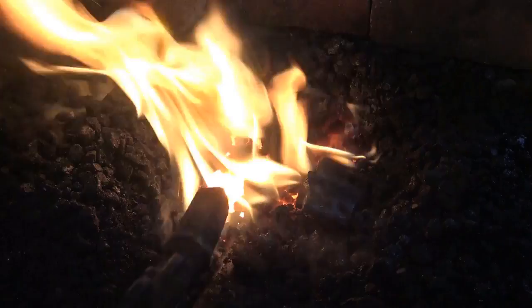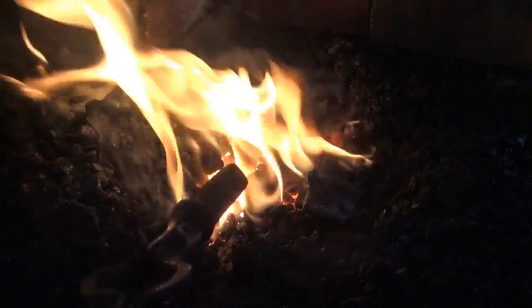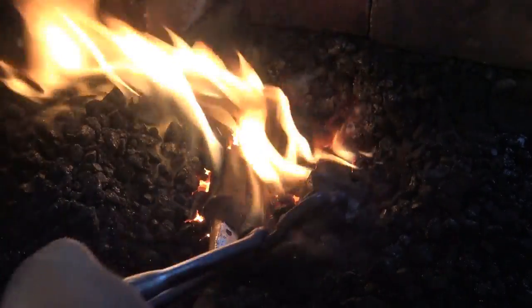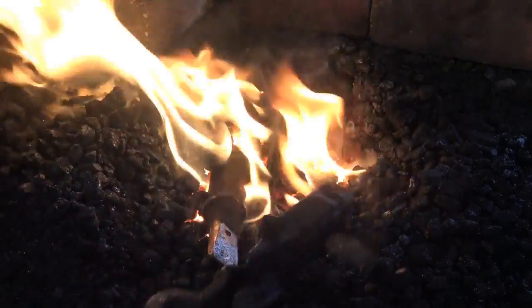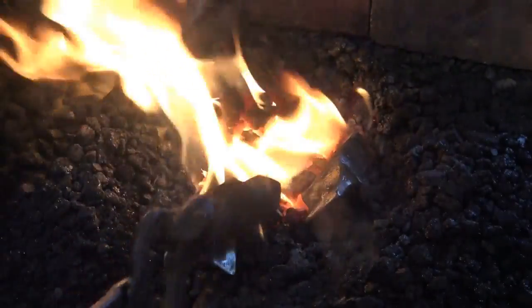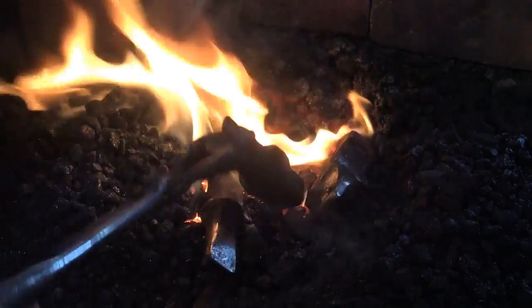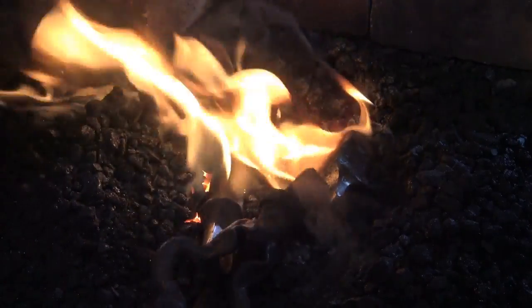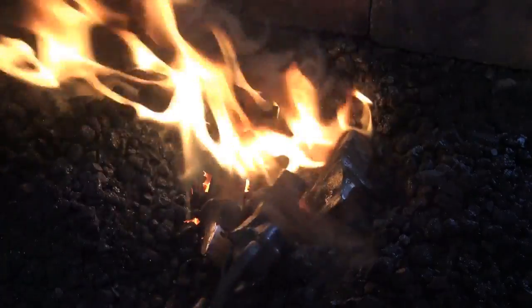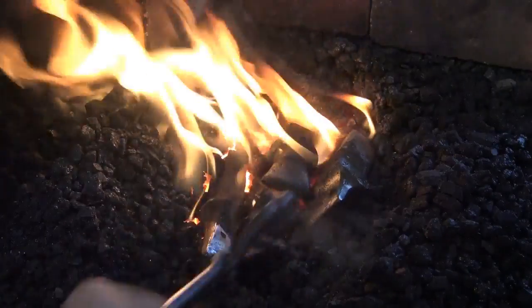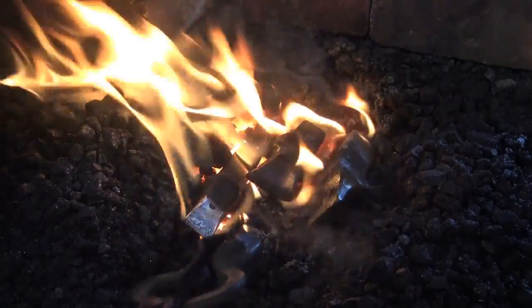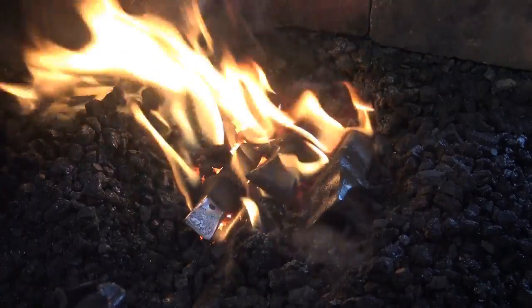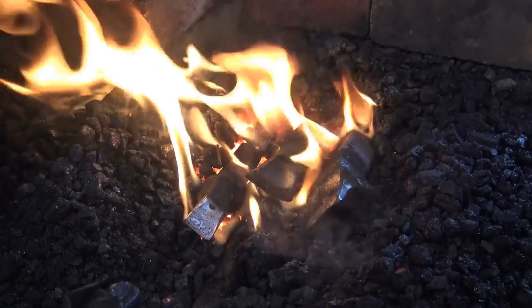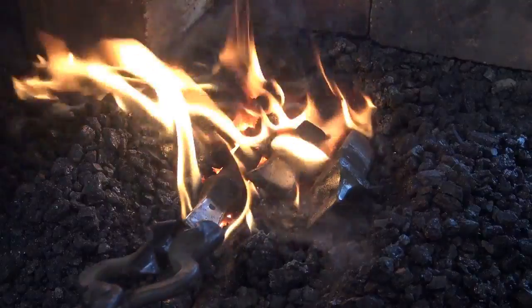Now I've got all three of these tools in here preheating. Most tool steels recommend a soak around 1200 degrees, so that's kind of what I'm theoretically going for. 1200 is just below the incandescent range. In other words, if it's glowing red, you've probably got it too hot. So I just want to let these soak for a while. And again, I'm just doing this by intuition and by experience because I have no perfect temperature control.